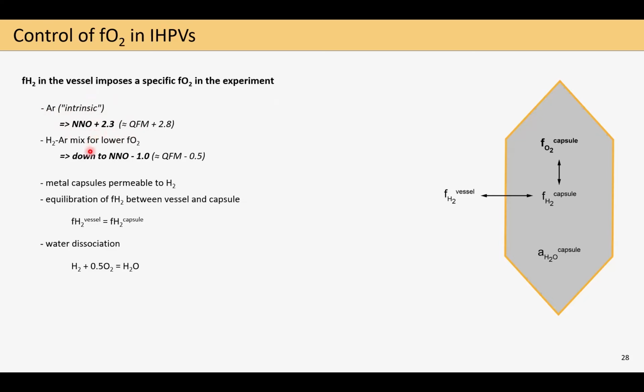And now, using the hydrogen system I just presented on the previous slides, we can add some hydrogen to this argon and thereby lower the imposed fO2 conditions, where currently we are capable of reaching up to roughly conditions of NNO-1. More reducing, I would not go in our vessels currently. And for the fO2 buffering, we're taking advantage of the principle that metal capsules are generally permeable to hydrogen, meaning that the fugacity of hydrogen in the vessel and the capsule will equilibrate during the experiment, as shown here in this sketch, where the hydrogen entering the capsule